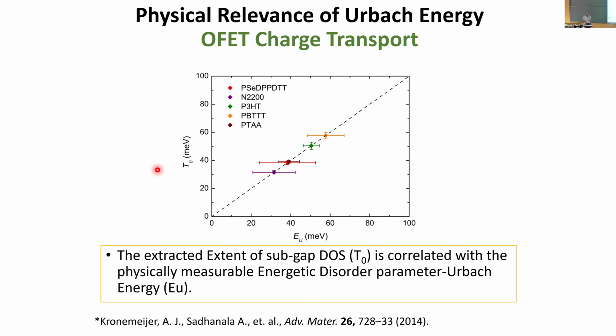This took a lot of time. Now what we found surprisingly is this parameter is exactly equal to the Urbach energy error range, which is not unusual, because in Urbach energy you're essentially looking at the density of states below the band gap and trying to quantify the width associated with it. So this relates directly, which helps because before even making an FET, you can take your material, measure what Urbach energy it demonstrates, and qualitatively predict what potential application it can have in FETs.